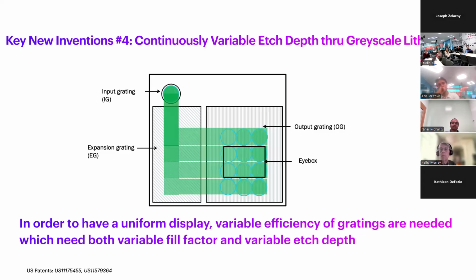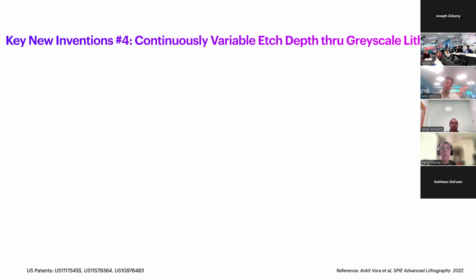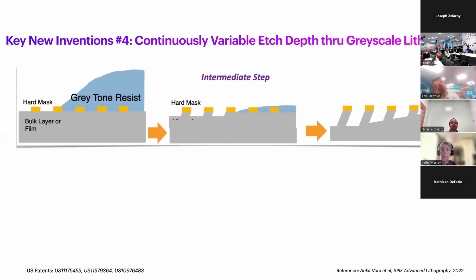While changing the duty cycle, which we call variable duty cycle, is trivial considering the decades of advancements in lithography in the semiconductor industry, continuously variable etch depth is a major challenge to achieve at scale. A fast and scalable method to create continuously variable etch depth is to use a lithographic process in conjunction with etch, where you have a variable thickness resist called the grey tone resist, and when you etch, you expose different areas of the gratings at different times.